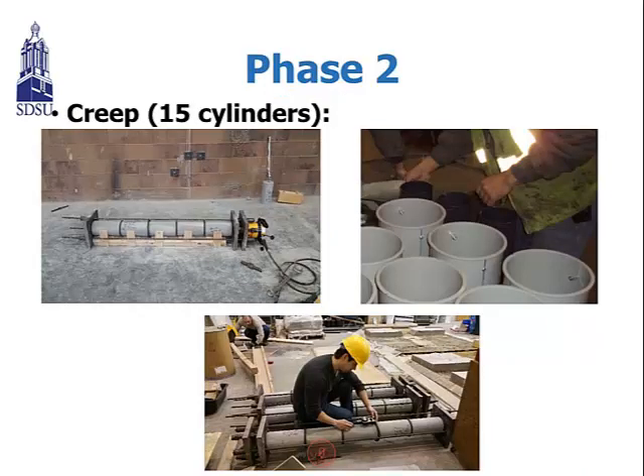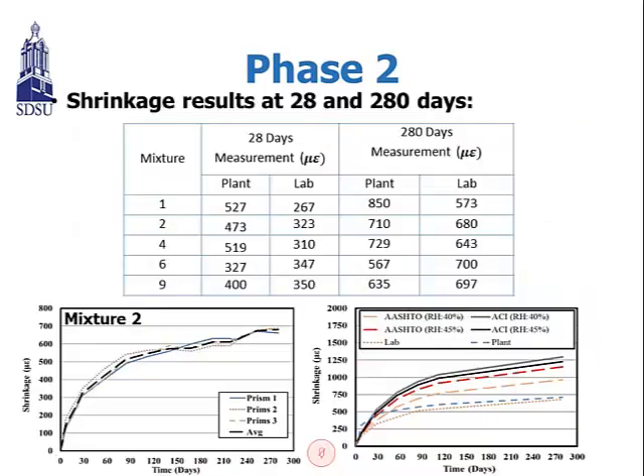And here's a creep 15 cylinder. For the creep testing, we just fabricated creep specimens at the plant only. And my graduate student measured the creep strain, as you can see at the bottom of the slide. And then here is the shrinkage result for 28 and then 280 days. And as you know, we selected the mixtures 1, 2, 4, 6, 9. And then you can see the 28-day measurement, plant and lab. There's some difference, plant and lab. And also you can see the difference in the 280 days measurement.